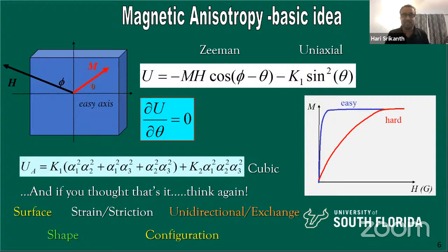Students can do this all the time. And that determines essentially the direction of the magnetization. And as you can see, it's a competition between two important energies. When you apply a magnetic field, you have the Zeeman term, and then you have the anisotropy. And that's exactly what results in the shape of the magnetization curves.